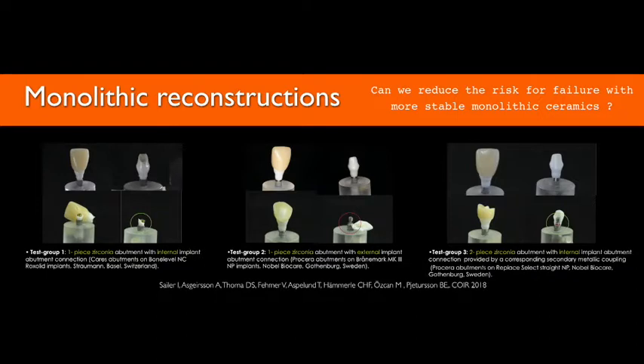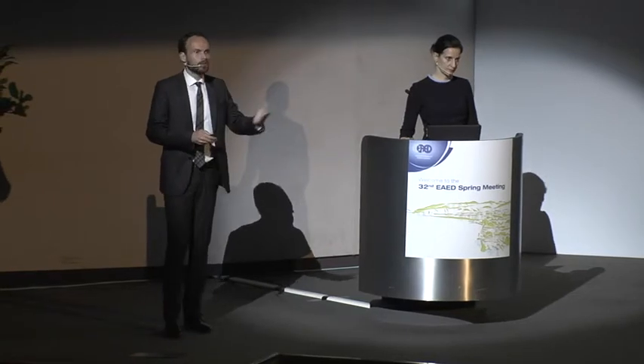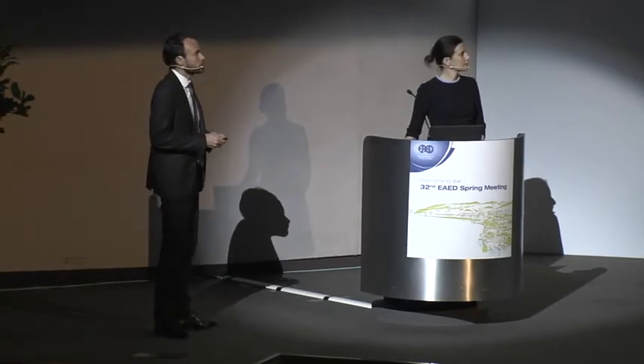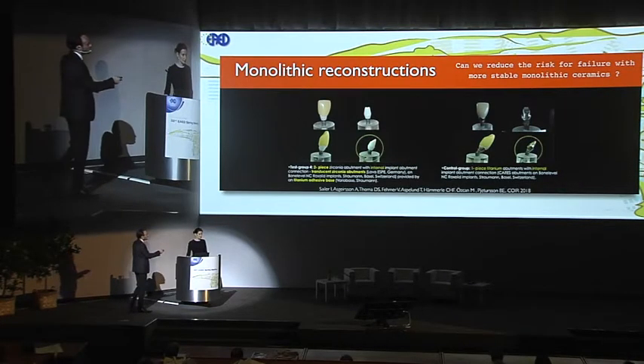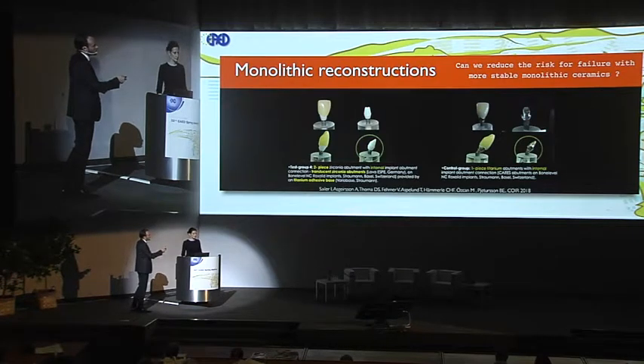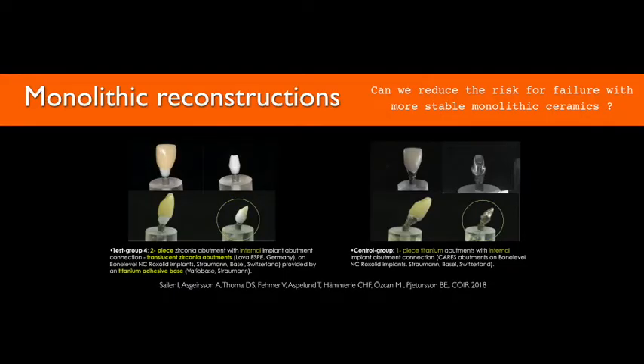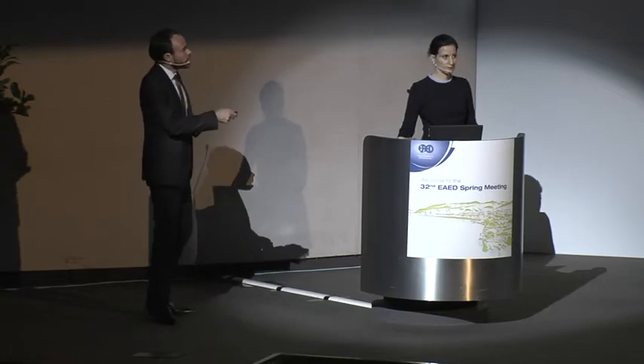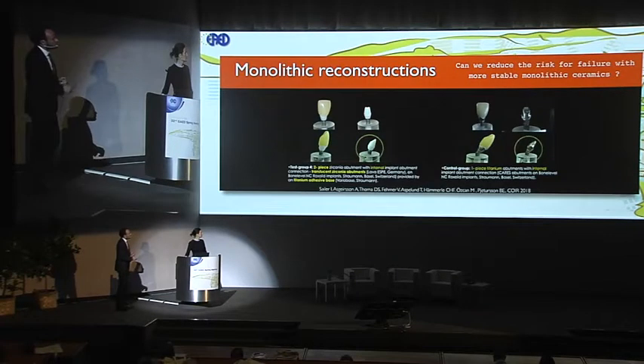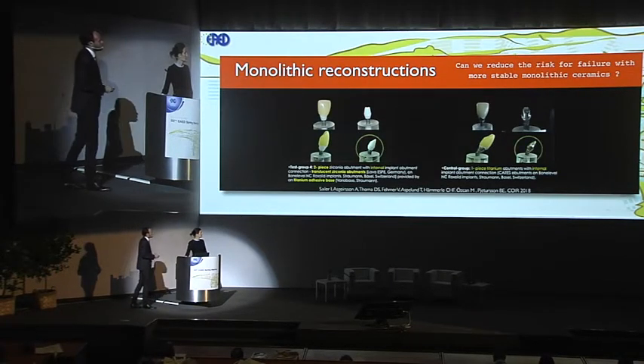So looking into this project, now finally published in 2018, we compared the complete zirconia abutments with the gold standard, which is basically the titanium abutment, and then the new type of reconstructive combination with the Ti base. As you can see here, we see only complete fractures on the zirconia. Then we see the behavior of the gold standard, the titanium abutment. It's just bending until the screw head fractures. And then you see the same behavior on the titanium resin base with the abutment on top of it.